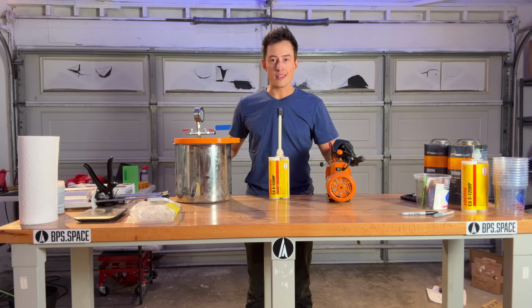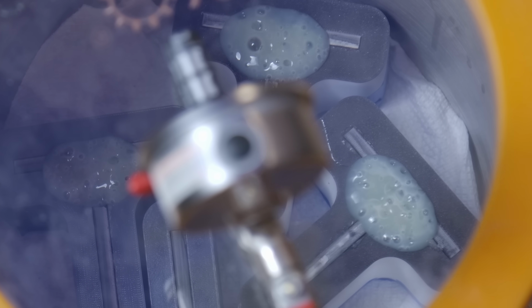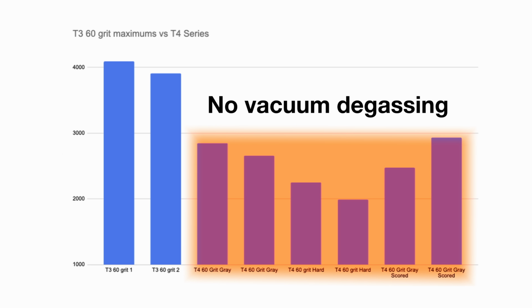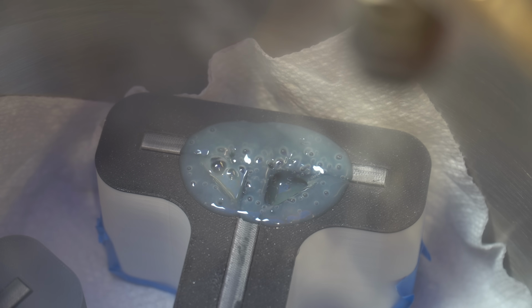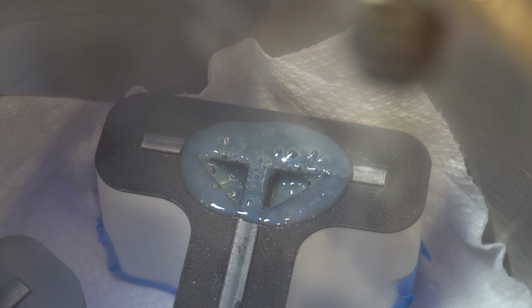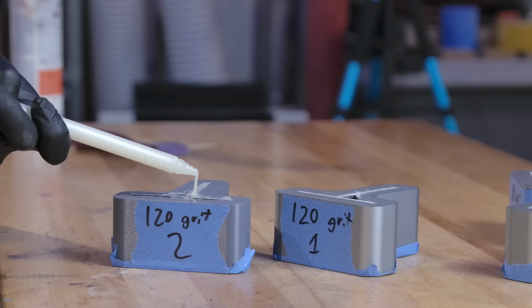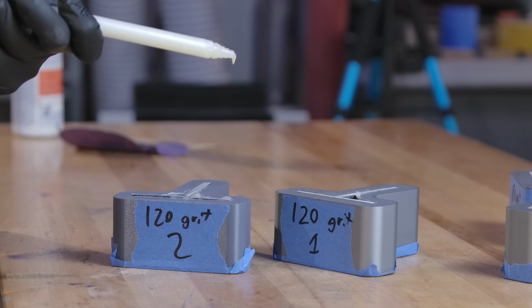Vacuum degassing. During the first round of tests, I degassed in the mold, but I found that it made loading the epoxy much less consistent, so I neglected it on this more recent round. The vacuum chamber made the epoxy expand so much that it bubbled out and over the mold, which meant I had to refill the epoxy, then re-degas in a couple of steps until that stopped happening.